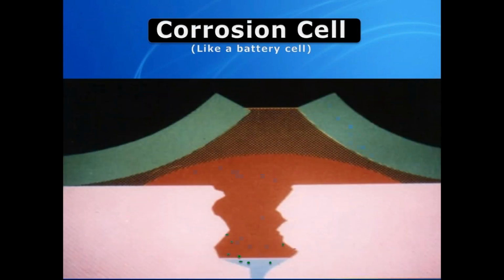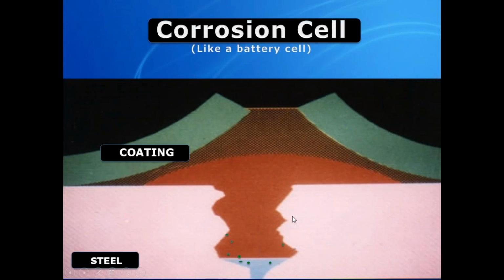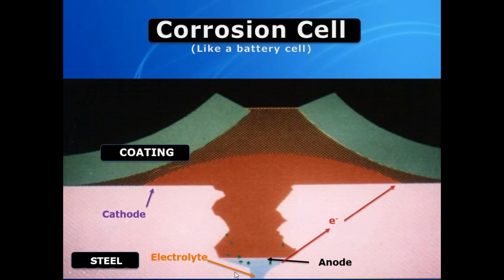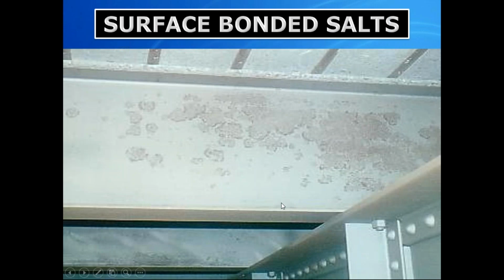The corrosion cell, which we've all seen over the years, is like a cell battery. To explain it a little bit more, if you have a coating applied to the steel, and say over here on the left-hand side there are no salts, no contaminants whatsoever, when the moisture passes through the coating, it just goes in and right back out because there's no metallic pathway, no salt contamination, no electrolytes or anything. And when you do have salt, say the green dots are salts in there, it forms an electrolyte, it becomes a cathode, and here's your anode here, and you have the electron or metallic pathway, and it just continues with the corrosion process and keeps building up, and it'll continue to go all the way through to the steel.